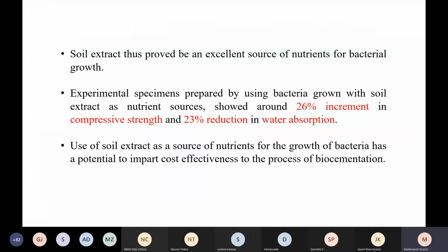So that means soil extract proved to be an excellent source of nutrients for bacterial growth. Isn't it? We didn't use any other nutrient. Then experimental specimens prepared by using bacteria grown in soil extract as nutrient sources showed around 26% increment in compressive strength and 23% reduction in water absorption. Use of soil extract as a source of nutrients for the growth of bacteria has a potential to impart cost effectiveness to the process of biocementation.